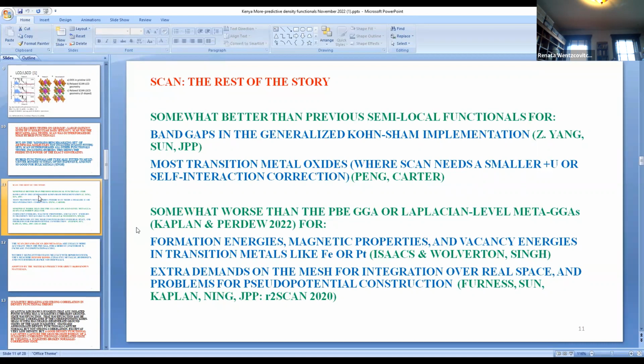For most of the transition metal oxides, other than the ones I just mentioned, SCAN still needs a core band self-interaction correction or a plus U correction, which can be found either empirically or non-empirically, but it's a material dependent parameter in any case. For most of the transition metal oxides, SCAN still needs a plus U correction to get an accurate result, but it turns out it needs a smaller value of this parameter than other functionals like LSDA or PBE. So SCAN is capturing more of the correct physics of these problems by itself.